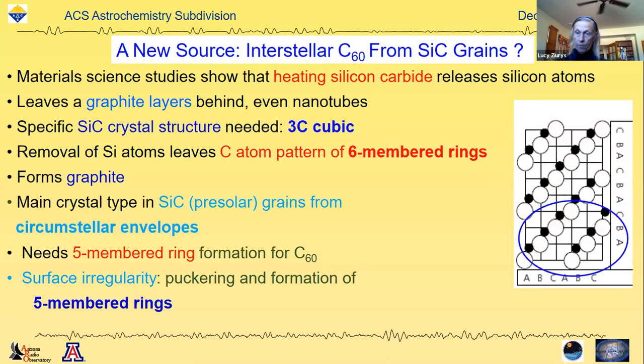And if you can imagine vaporizing the first three layers of the silicon carbide, you take the silicon off, and then you have an arrangement of 6 carbon atoms that just forms graphite naturally. This has been documented in the material science literature for years, and it's actually been used to create graphite for the semiconductor industry. Now, it just turns out that this 3C cubic structure is the most common crystal type for silicon carbide formed as dust grains in circumstellar envelopes.